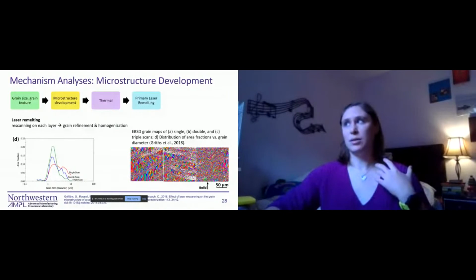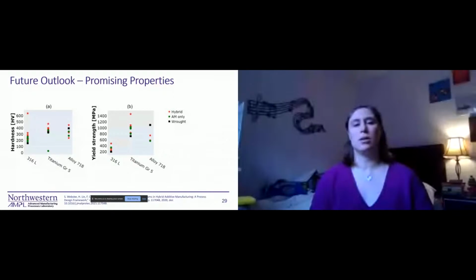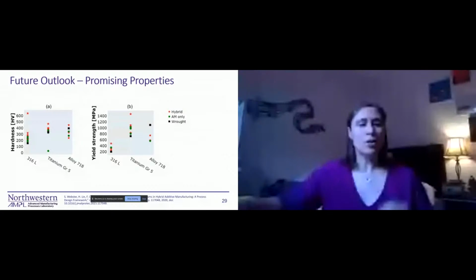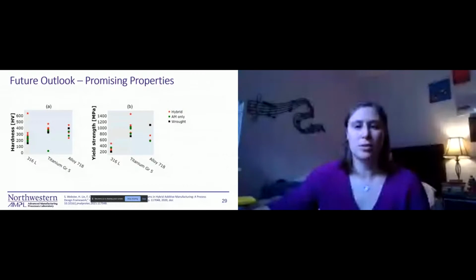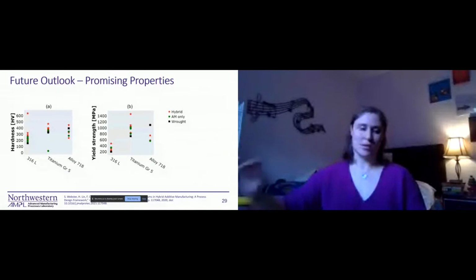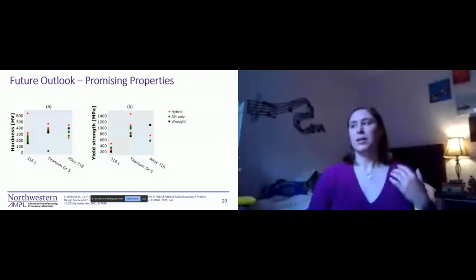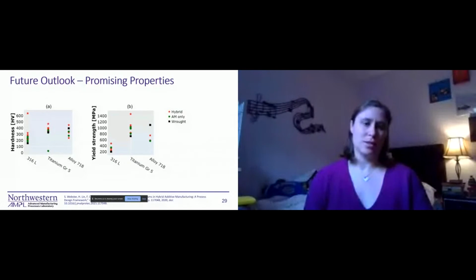Now looking out at the future of hybrid processes, first looking at the promising properties that have come from this research. In general, the maximum mechanical property values are achieved through hybrid processes as opposed to only AM processes. So the red stars are hybrids. You can see across the board that we can get better material properties with the exception of alloy 718 in this case, and that's because of the lack of heat treatment afterwards in this particular case.